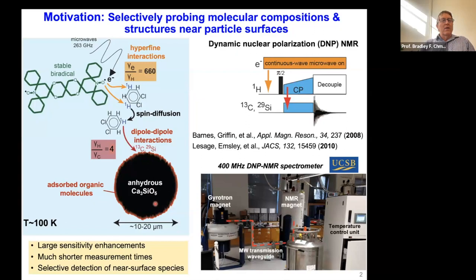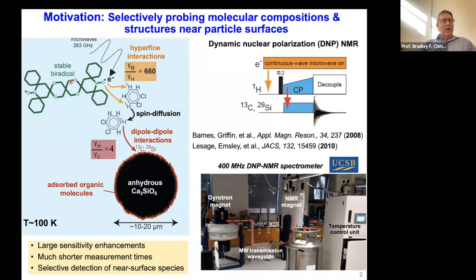Often these particles are many microns in size. The surface area of these 10-to-20 micron cement particles is going to be approximately one meter squared per gram — not enough surface spins to achieve a reasonable signal-to-noise for most of the NMR measurements we'd like to exploit. So we'd like to enhance the signal intensity, and the way it's been done builds on the shoulders of Bob Griffin's work and Alexander Barnes and others in Bob Griffin's group.